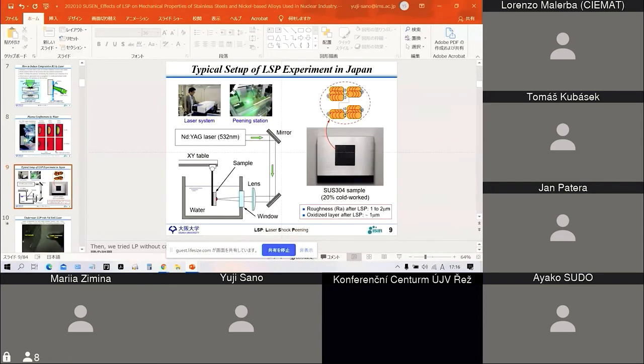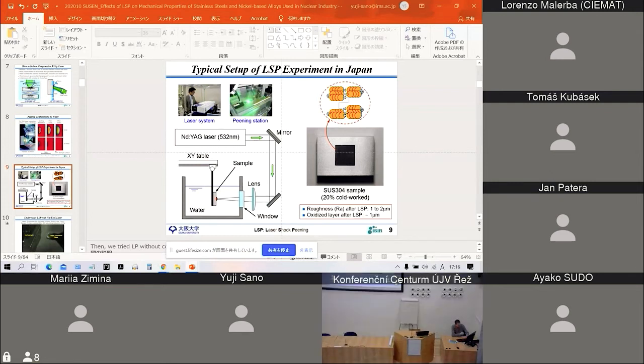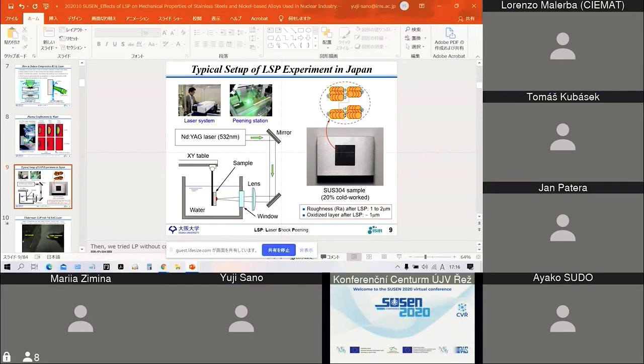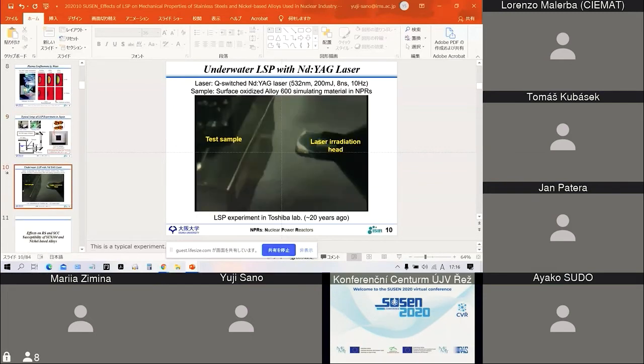This is a typical setup of our experiment. Here is the laser system. A laser pulse is delivered by mirrors and irradiated onto the material, submerged in water, through the lens and the windows. In this case, we drove the specimen two-dimensionally to cover a certain surface to make a compressive residual stress like this. Then we measure the residual stress by using the X-ray diffraction technique.